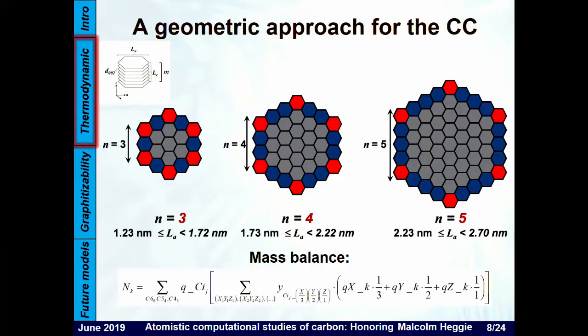After that, we can do a simple geometric model for the mass balance of the system. Here you can see a single graphenic plane, and for given values of La, you can make it as big as you want. This is to represent the effect of the growth of the crystallite when heat treatment is applied, for different increasing heat treatment temperatures. Below, you can have the associated mass balance equation. If you know La, you know everything about the geometry of your crystallites, and you can know the exact composition of it as a function of the species that you put on the gray, blue, and red hexagons.